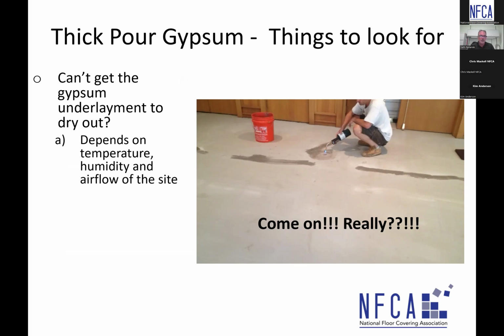And with gypsum that has a lot of water in it, while there is chemistry and hydration that happens, that water has to evaporate out. And to get it to dry, we have to have good temperature. We have to have good ambient humidity. We have to have good airflow. If we're sitting at cooler temperatures and high humidity and no airflow, nothing's going to dry. And that unfortunately happens on site because we don't have good conditions.